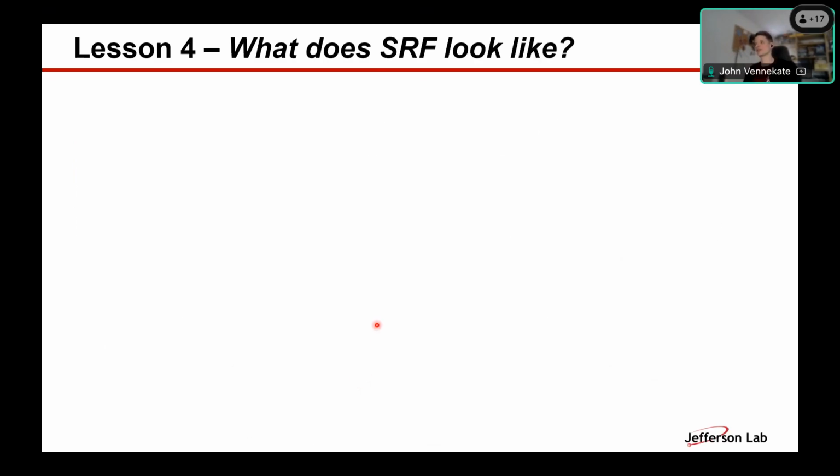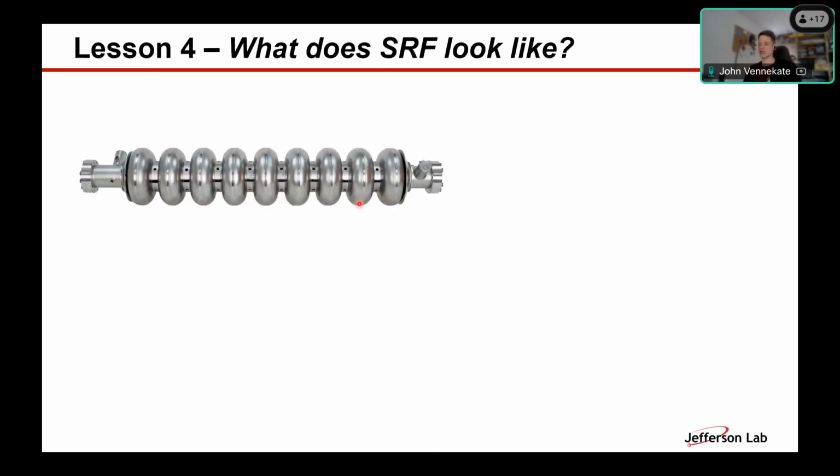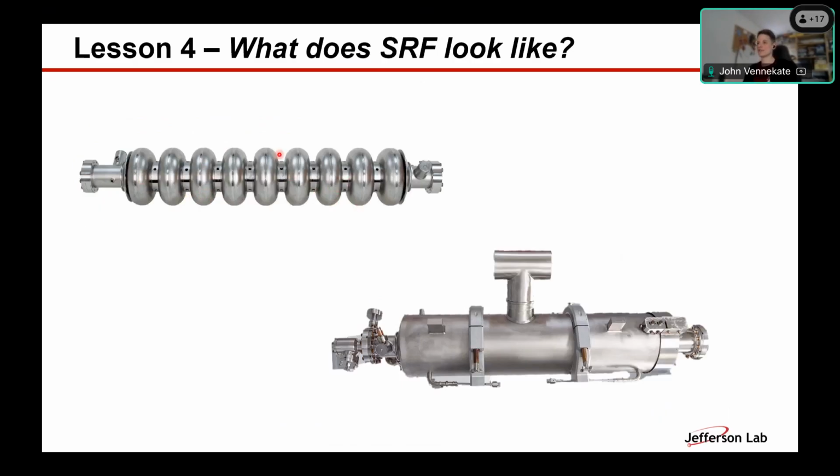When you then ask, what does SRF look like on a large scale, I just started you off with superconducting cavities made out of niobium. That's an elemental superconductor, and we like to go with high purity niobium. And then we have to get those cavities, you see over here, still superconducting, so we have to cool them down, as I said, super cool them down, and that we do with cryogens, and that means we have to introduce liquid helium. That's exactly what this 9-cell cavity, you count here a total of 9 cells over here, looks like in operation, because it will be put into a titanium helium vessel around it. Over here is a connection that hooks it then up to the cryo plant inside our cryo module.